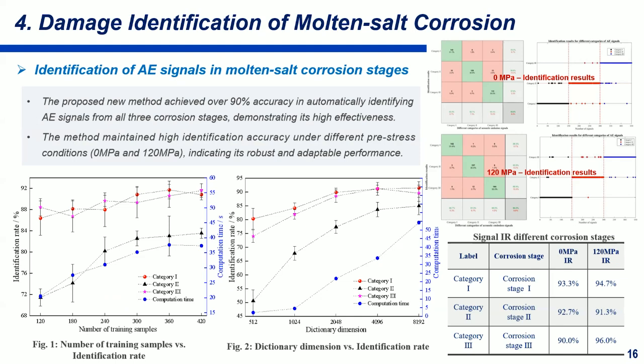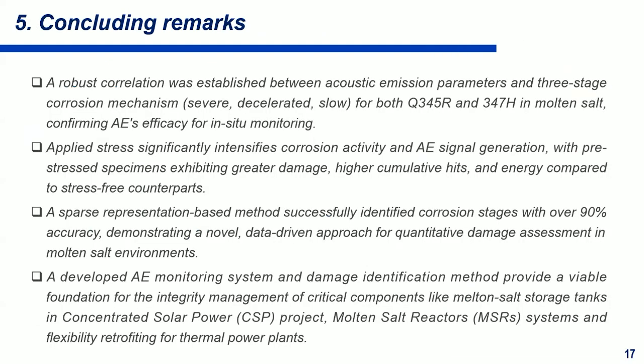The method maintained high identification accuracy under different stress conditions, indicating its robust and adaptable performance. Now, the concluding remarks. A robust correlation was established between the AE parameters and the three stages for both materials in molten salt, confirming AE's efficacy for in-situ monitoring. Applied stress significantly intensifies corrosion activities and AE signal generation.